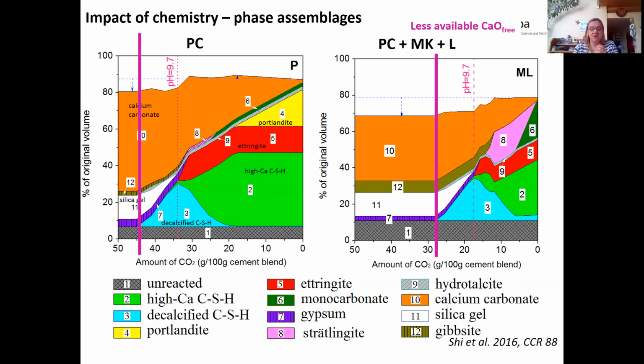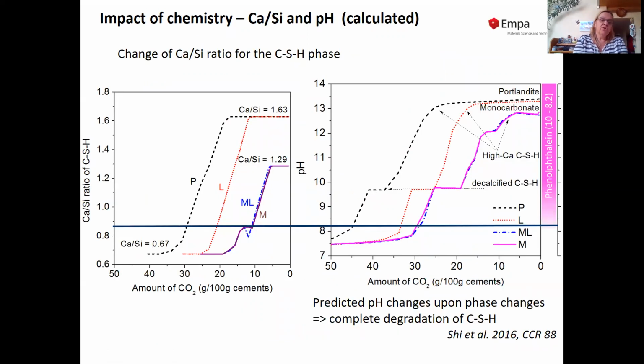And that's the second reason why they carbonate much faster, because they cannot bind so much CO2 when it comes in. And we can nicely use thermodynamic modeling to understand the differences and to calculate how much calcium oxide we have available. We also can compare the calculated calcium to silica ratio of the CSH for the four cases. We can see here, again, we can add more CO2 in the presence of portlandite than we can for